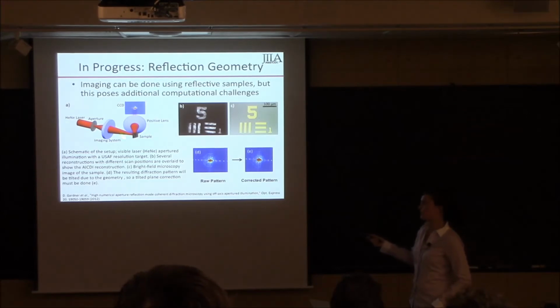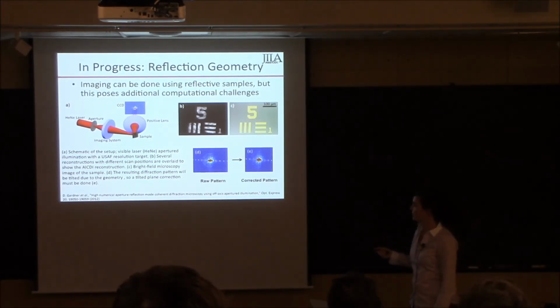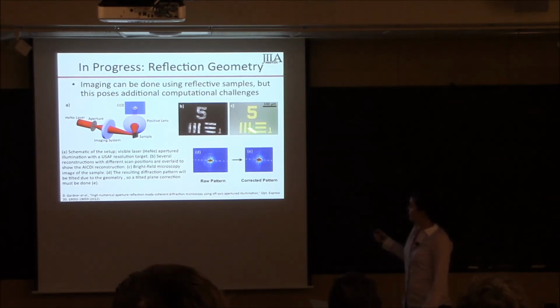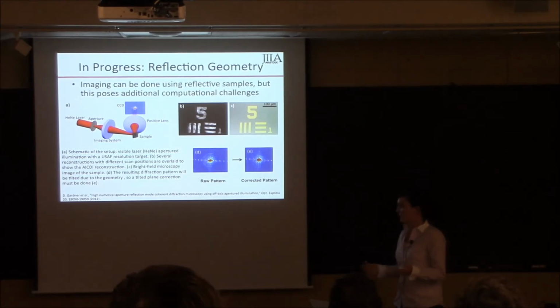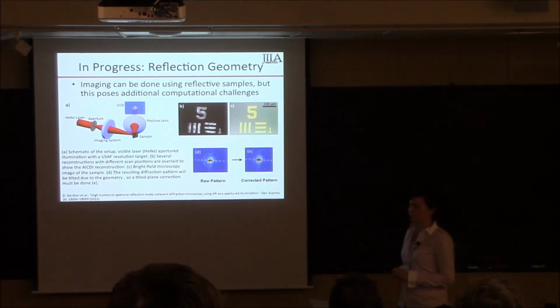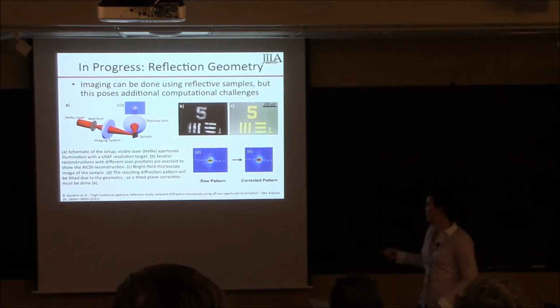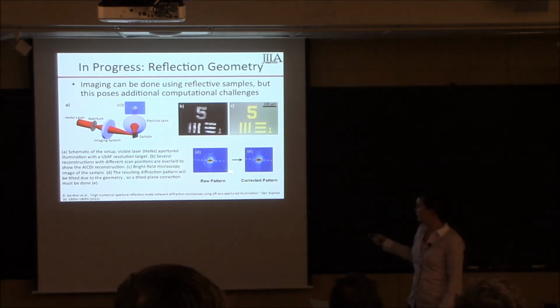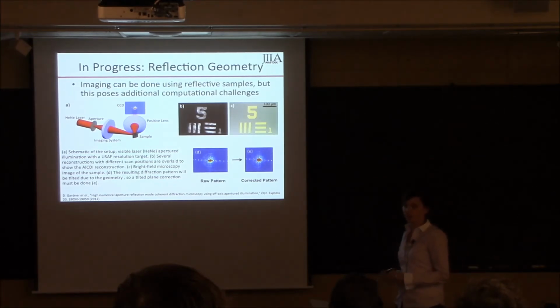So you can see the setup for that, where the sample's at 45 degrees, and then the diffraction pattern is collected. Here's an optical microscope image of the sample and some reconstructions. So you might notice, if you think about reflection geometry, that you're going to get some distortion in the horizontal direction due to the geometry of the setup. So that's seen in the diffraction pattern here, where the spacing of the peaks on the left is different from the spacing of the peaks on the right.